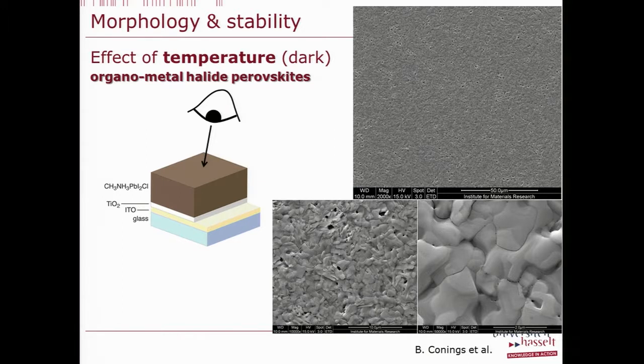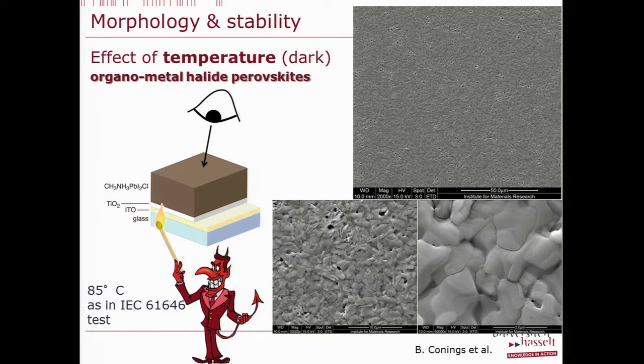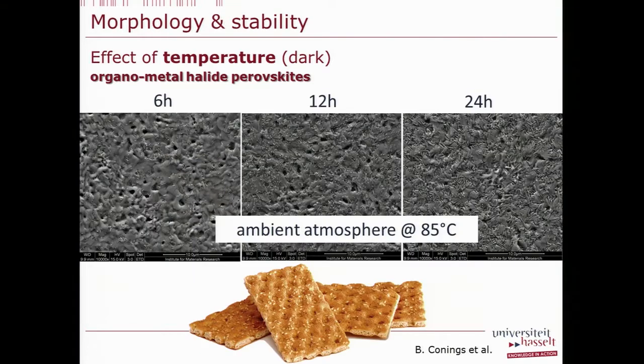And what we've seen, if we go to 85 degrees Celsius in ambient conditions, also there we see some changes of morphology. I don't know if from your side you can see it, but on the morphology you see that there are some additional features forming. It's like these tracks with some seeds on top. That's what we are making when we bring these perovskites to these temperatures.